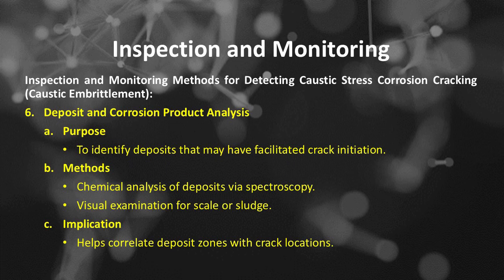Inspection and monitoring methods for detecting caustic embrittlement. Number 6 is deposit and corrosion product analysis. It is purposed to identify deposits that may have facilitated crack initiation. Methods to detect deposits and corrosion include chemical analysis of deposits via spectroscopy, and visual examination for scale or sludge. And the implication is to help correlate deposit zones with crack locations.